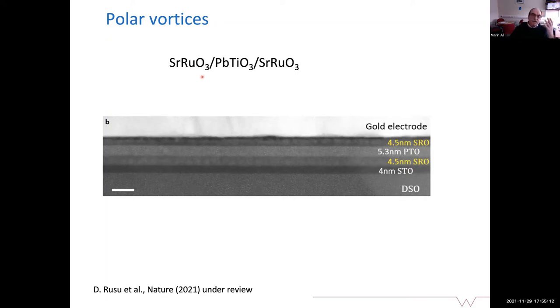Why is that? It's just because it grows very nicely on strontium titanate, on dysprosium scandate, and all these substrates which are used to tune the embedded misfit strain in ferroelectric layers. And then you see here the low magnification TEM of the structure. We have about 4.5 nanometers, so practically 9 to 10 unit cells of strontium ruthenate and 12 unit cells of lead titanate.